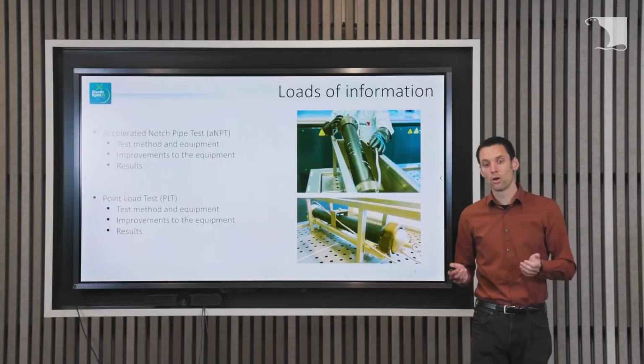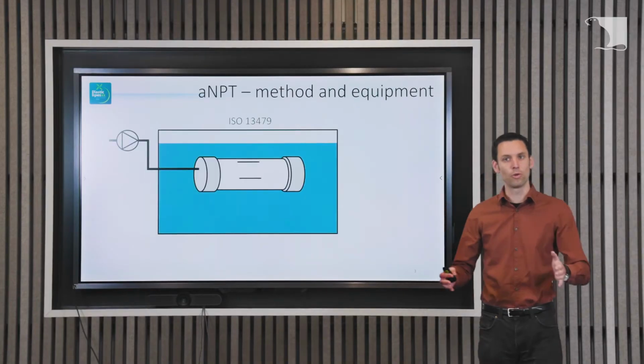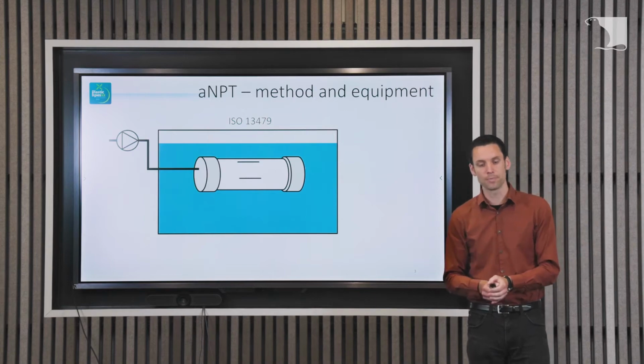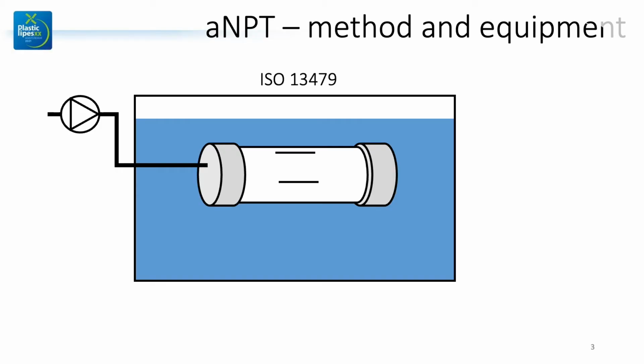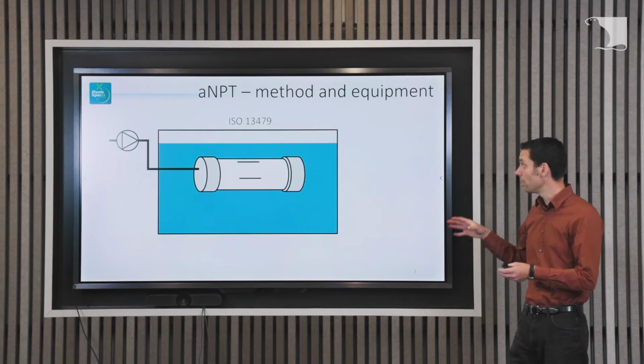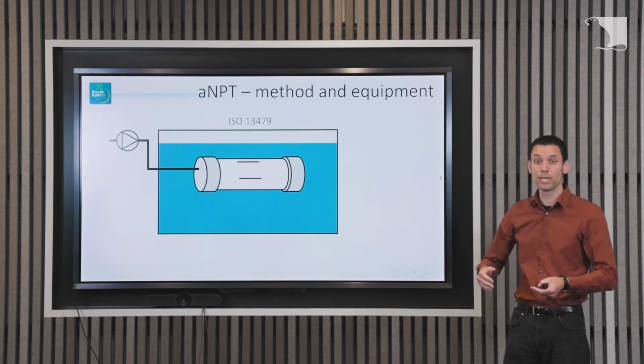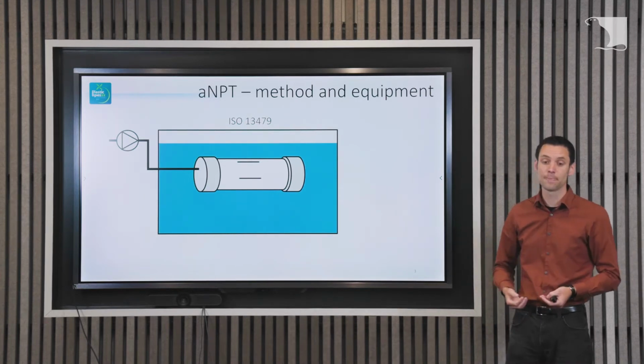First up is the accelerated notch pipe test. Or perhaps better, let's start with the normal notch pipe test. So what's the normal notch pipe test? Well, here you see a plastic pipe, a polyethylene pipe, which is installed in a water bath. And we have 4 notches around the circumference. The water bath is at 80 degrees centigrade, so we have a higher temperature to accelerate it. We have a pump to pressurize the pipe. So it's sort of a hydrostatic pressure test, but now we have 4 notches on the circumference.